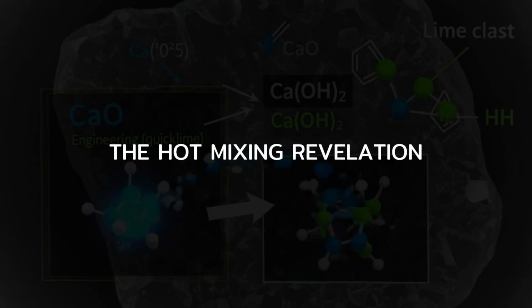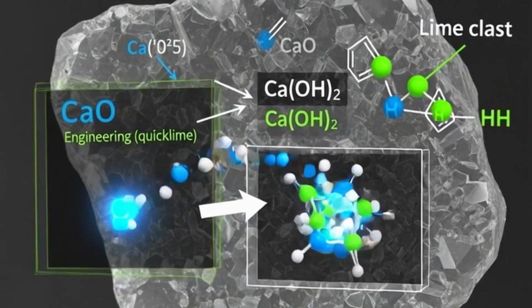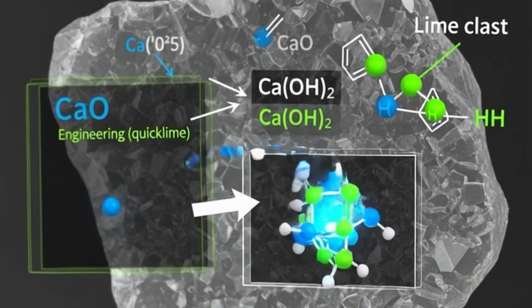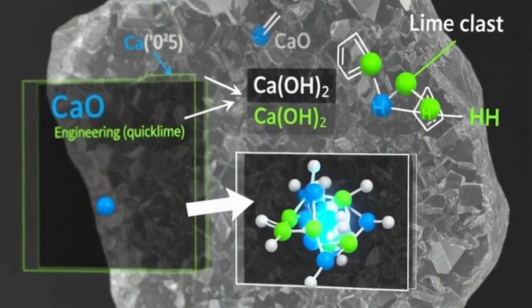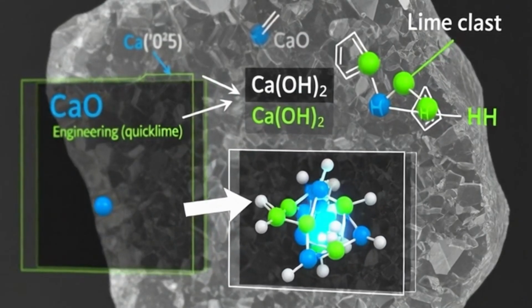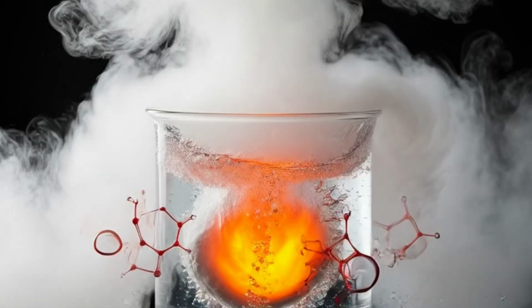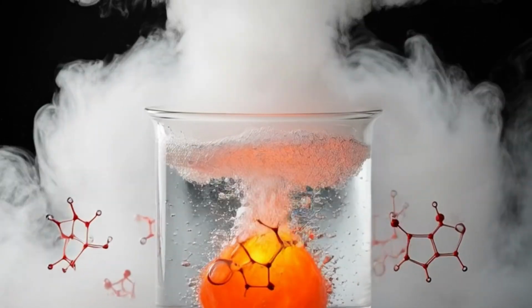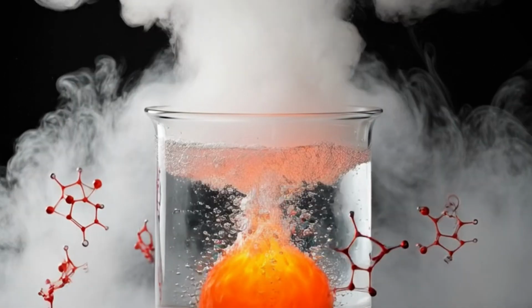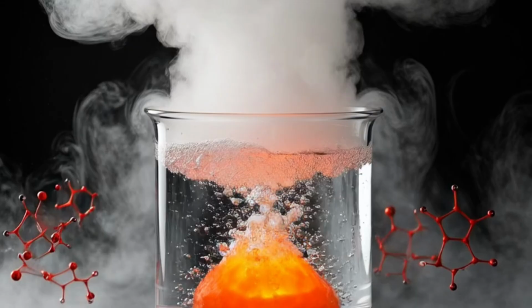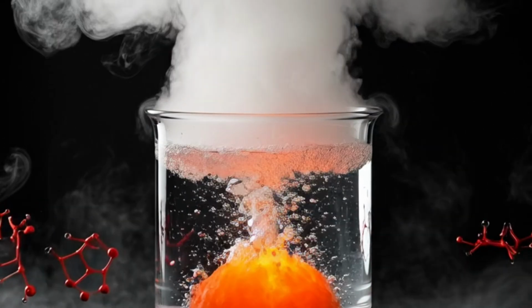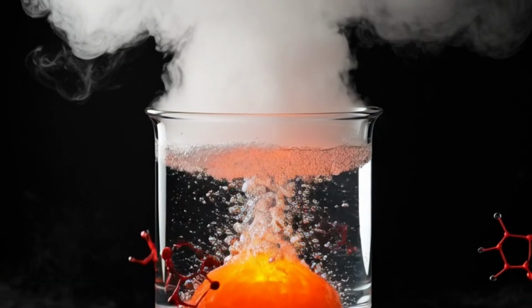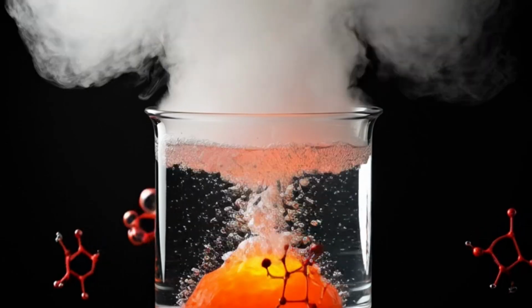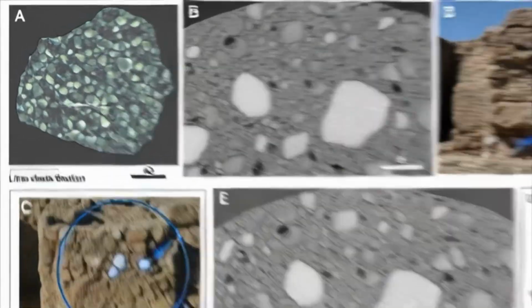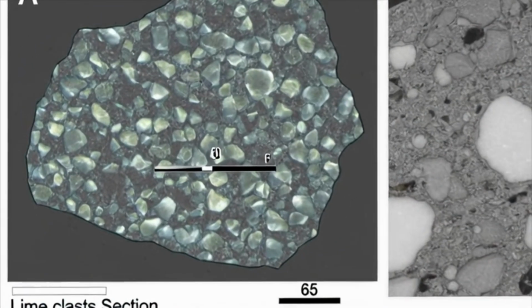The hot mixing revelation. MIT analysis showed the lime clasts were quicklime, calcium oxide, not calcium hydroxide. This means Romans mixed quicklime directly into the concrete, without slaking it first. This sounds wrong. Quicklime reacts violently with water. It's an exothermic reaction; it releases heat and creates steam. Why would you add this to a concrete mix? It seems dangerous, unpredictable, poor practice.